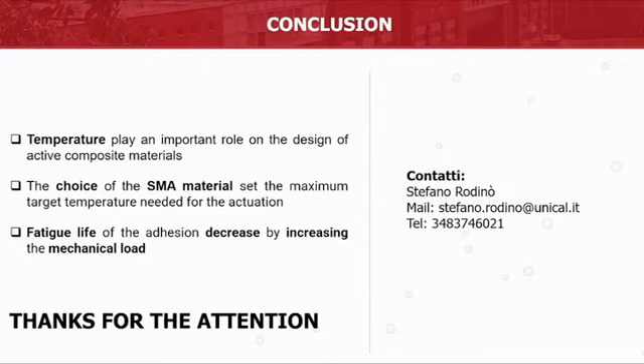The temperature for sure plays a very important role in the design of the active composite material, and also the choice of the SMA, the type of SMA material, sets the maximum temperature that you have to reach to fully activate the SMA material. And another thing is that the fatigue life of the adhesion of the material decreases with the increase of the mechanical load.